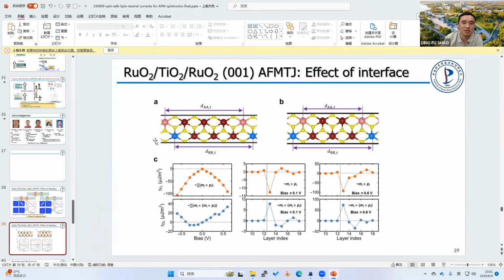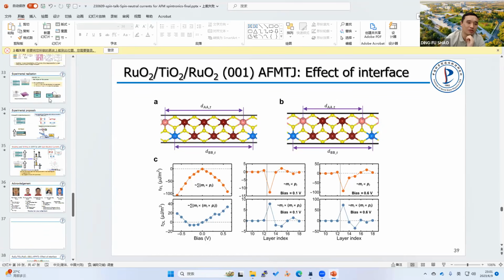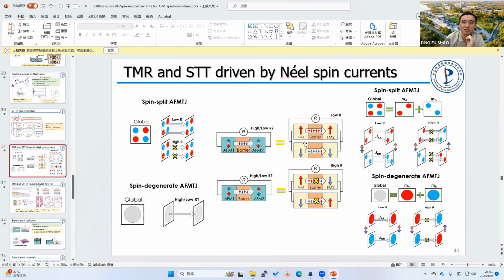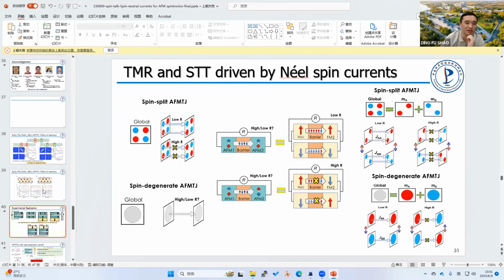And we think this is quite straightforward because, unlike the previous consideration of the STT and the TMR, which were due to some coupling of the interfacial moments to the staggered spin density in the bulk, we in fact have a sublattice-resolved current. Because the current is very strong, we can indeed divide this antiferromagnetic tunnel junction into two ferromagnetic tunnel junctions. So in this case, like showing here,